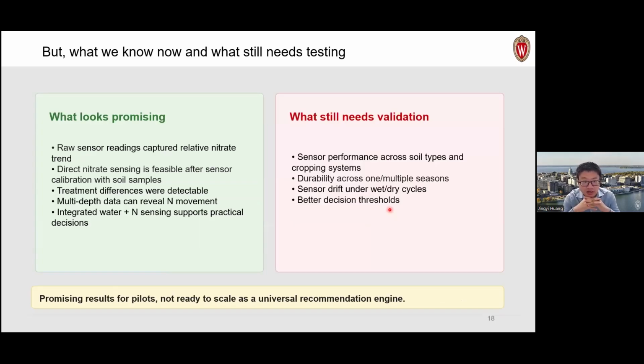So far, what we have covered is that you can have a sensor designed to measure nitrate in the lab and in the field environment. Based on the preliminary lab and field experiments, we found that the raw reading could capture the relative nitrogen trend. And if you calibrate the sensor with a real in-season soil sample test, it's possible to get the direct or absolute soil nitrate in ppm. Then we can use these sensor technologies to detect treatment differences. If you place your sensor at multiple depths, based on the increase and decrease of nitrate at different depths, you can also infer at which depths the nitrogen has been quickly depleted, either due to plant uptake or due to leaching.